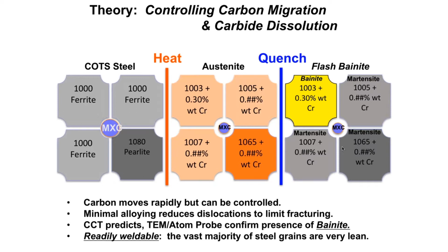And what's also very interesting is we have found that this material is very readily weldable at room temperature. And we think one of the reasons may be is because the vast majority of the steel grains are actually very lean. First of all, because we're using lean alloys, but second of all, because over half of the microstructure is a very lean chemistry, because we've trapped our carbon in pockets of high carbon regions and carbides.